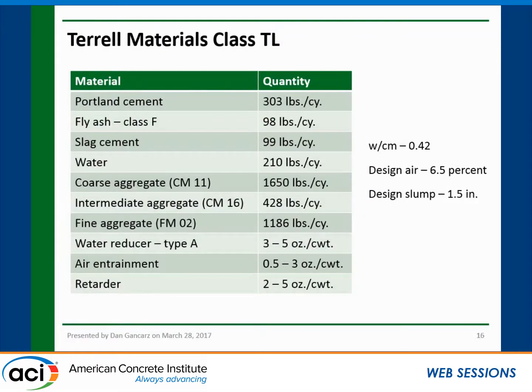So this is one of the mixes that was used on the I-90 construction. They placed about 25,000 cubic yards on one of the projects. It's about 40% SEM replacement, 505 pounds total cementitious, 0.42 water cement ratio, and then, as I mentioned, the 2 coarse aggregate requirement, and then your typical water reducer, air entrainment, retarder. And this mix was used for the performance-related construction specification, and it achieved over 100% for strength and air content, which I think partly has to do with the producer's focus on quality control. They were focused on maintaining a consistent air loss between the plant and the job site, and then also monitoring aggregate moisture, making sure their process was consistent to achieve those requirements.